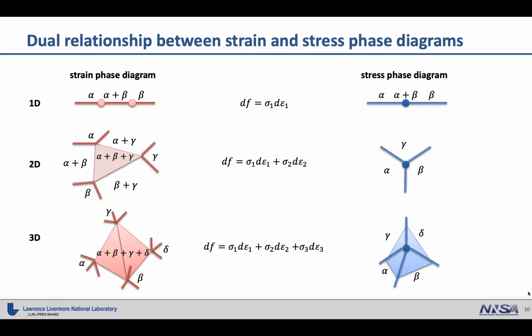And here's a simpler representation of the phase diagrams for 1D strain, 2D strain, and 3D strains. I'll just give one example. Like in the 1D case, for the strain phase diagram, the 2-phase region is actually a segment, but in the stress phase diagram, it's just a point, like a 2-phase point. And similarly, in the 2D strain state, it's a triple point of 3-phase coexistence, corresponding to a triangular region in the strain phase diagram. And for the 3D, it becomes a tetrahedral 4-phase region.